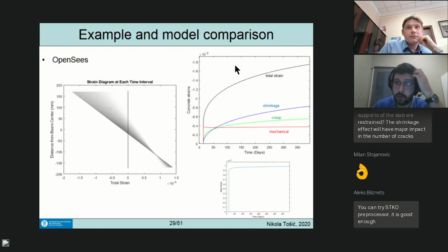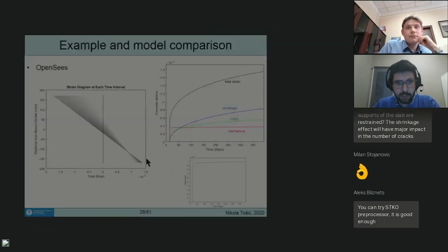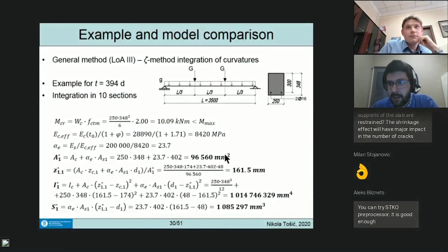And you can decompose concrete strain. This is the total strain, but this is the shrinkage component. You see that it's a lot because, of course, the experiment had like 0.83 per mille of shrinkage strain, creep, and mechanical strain. Even further, you can decompose this, but they didn't plot it here. Even creep and shrinkage, you can separate into basic and drying. So you can see the impacts, but for such a low strength concrete, the basic component is not going to be so big, at least for shrinkage. So this is what the model offers you.